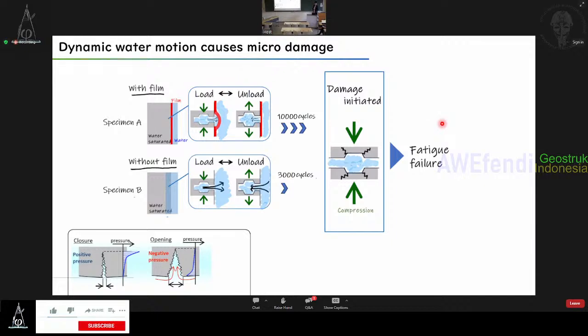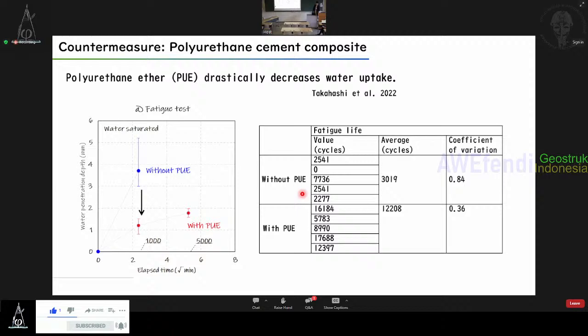Such an idea is related to the previous mechanism presented by Professor Maekawa in 2013. And one more slide from my side is how to mitigate such underwater fatigue. One possible countermeasure is to use polymer cement composite. As we published with Shingo, polyurethane ether is one polymer designed by my company, and that polymer drastically decreases water uptake.